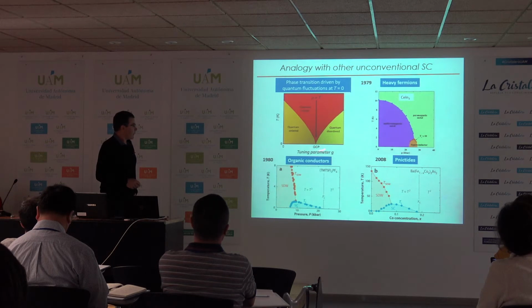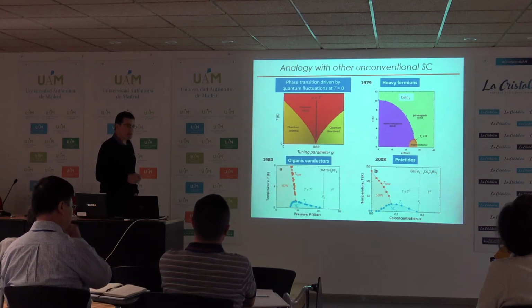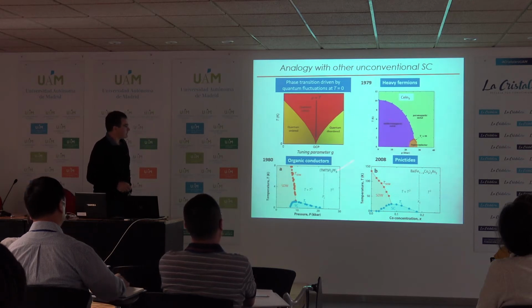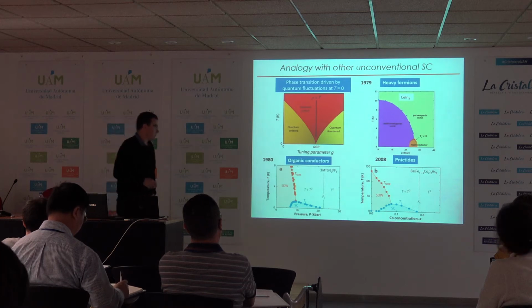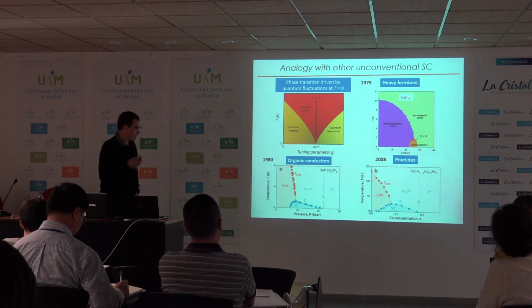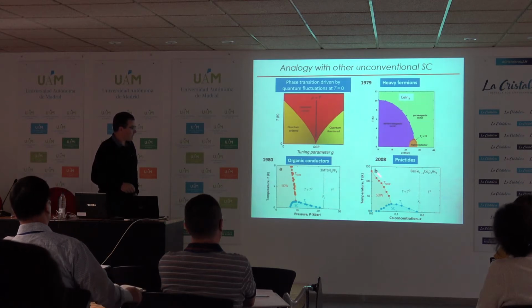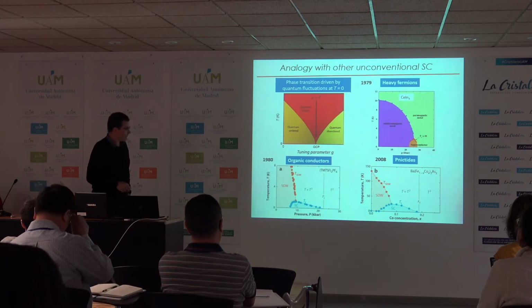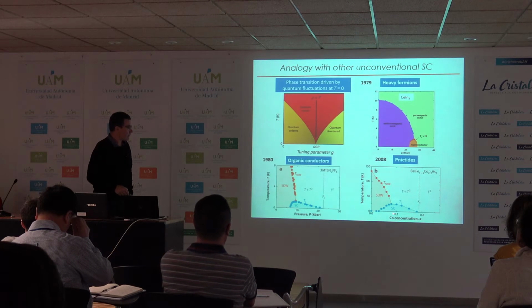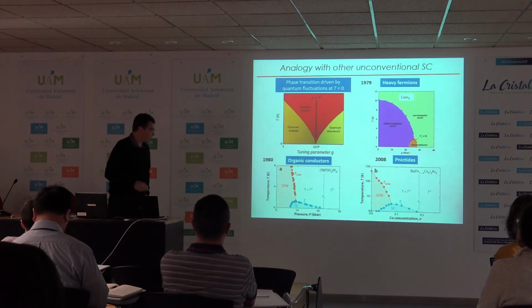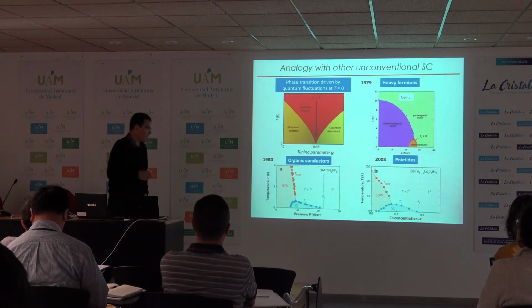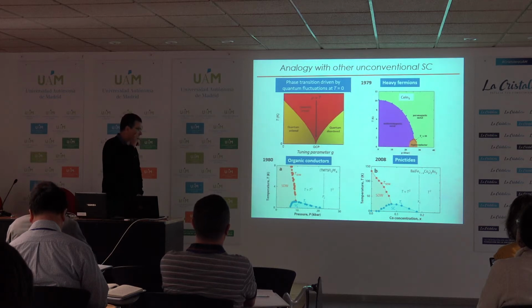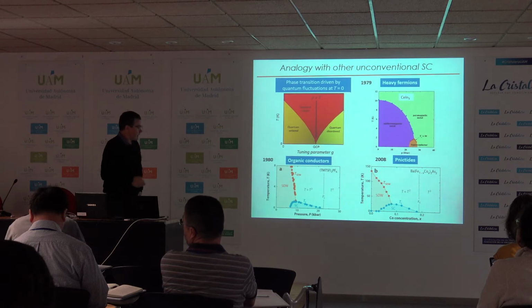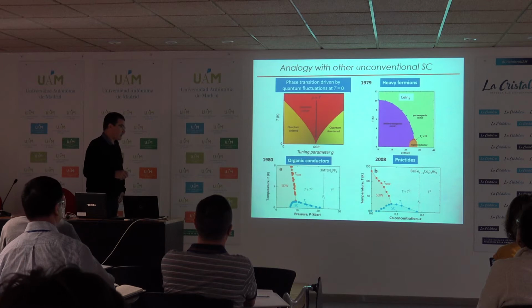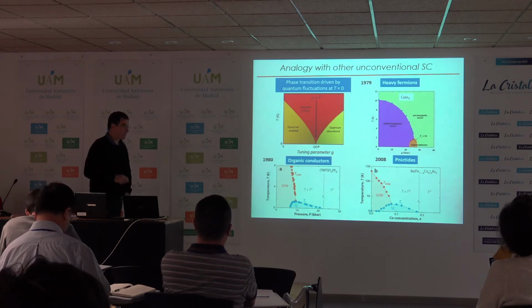And around this point, in many families, such as this one, you can see unconventional superconductivity appear. So, for instance, if you look at the pnictides, which are a very good example of that, you have itinerant antiferromagnetism for the parent compound. And when you dope, you see that the temperature of this antiferromagnetic spin density wave state goes down, and where the temperature should go to 0, you see this superconducting dome appear, where the temperature can be as high as 50 Kelvin. And this superconducting dome is believed to be controlled by the quantum critical point due to antiferromagnetic fluctuation.